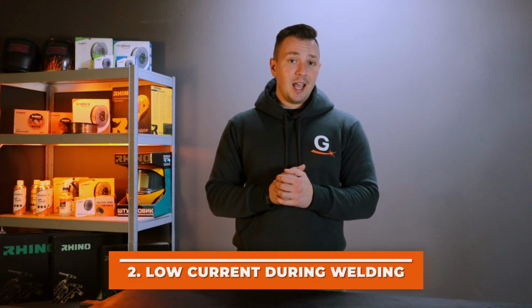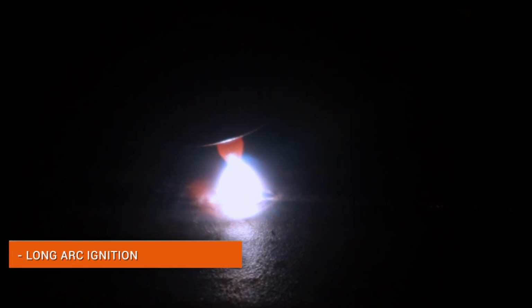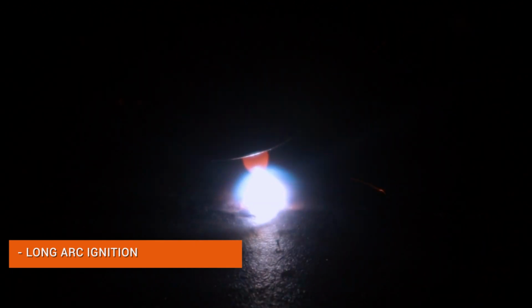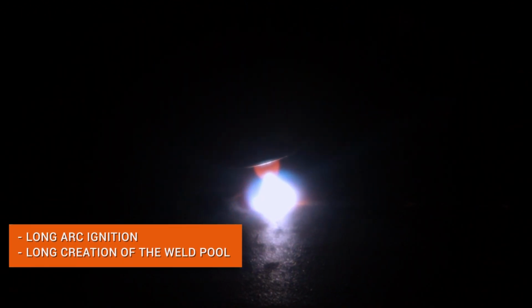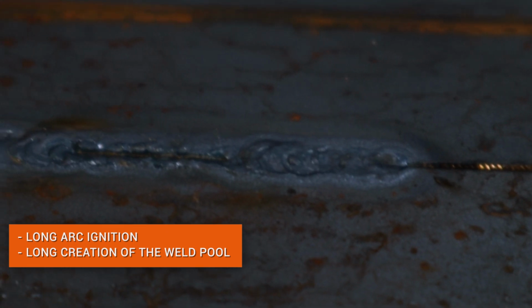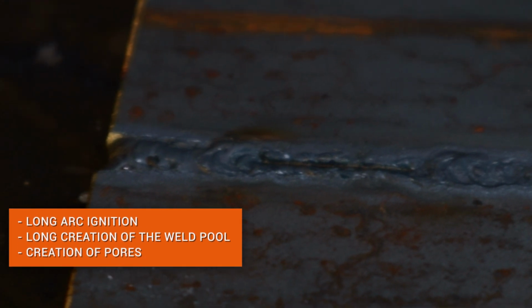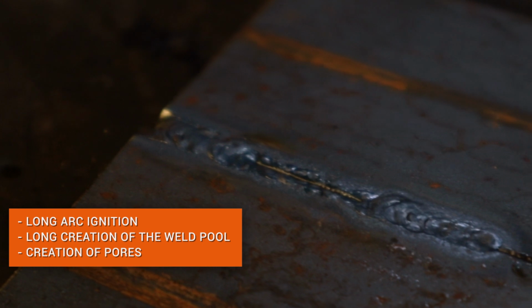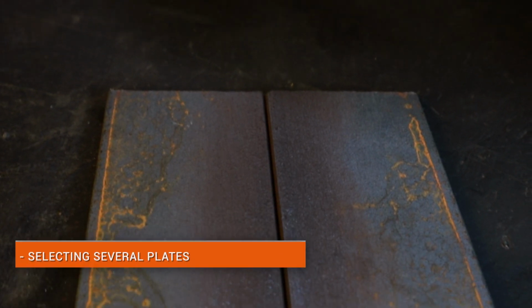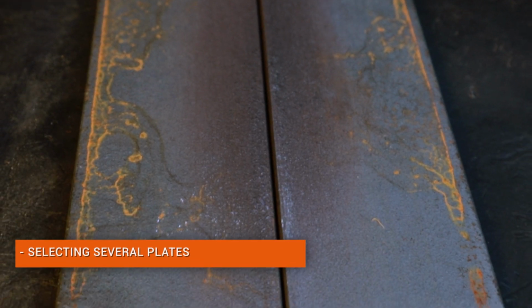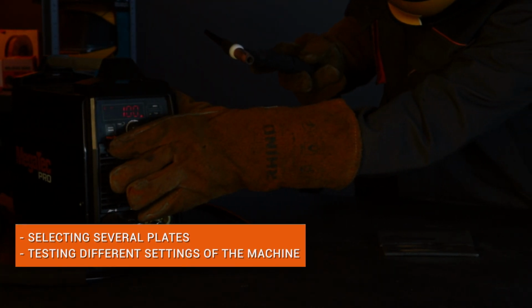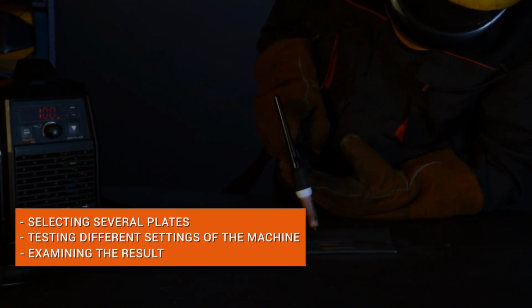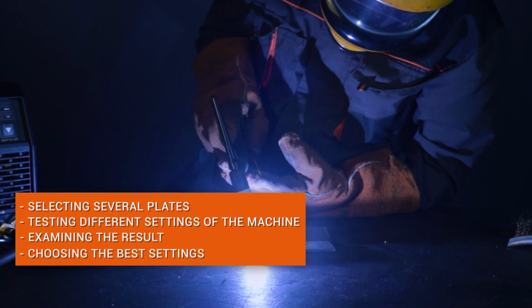Mistake number 2. Setting a low current. Low current leads to prolonged arc ignition, arc instability, and prolonged weld pool formation. Taken together, these factors can lead to overheating of certain areas of the workpiece, poor quality welds, and damage to consumables. One of the simplest solutions used by almost all professional welders: select several plates of the same metal and thickness as the main structure. We test different currents on them. At the end, we inspect the welds and choose the best current settings for the main structure.